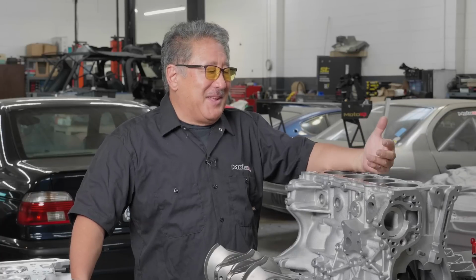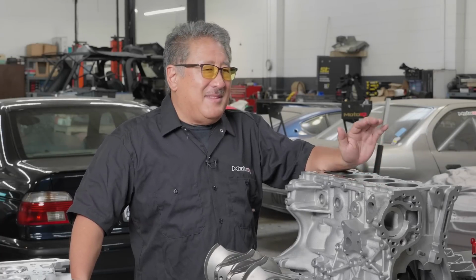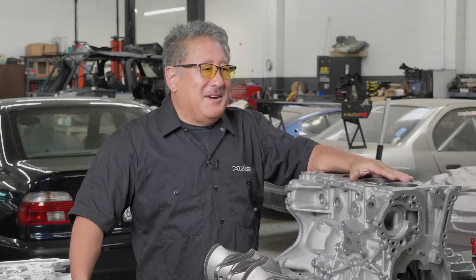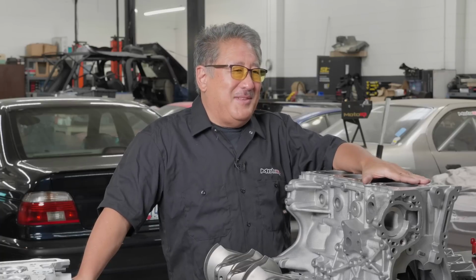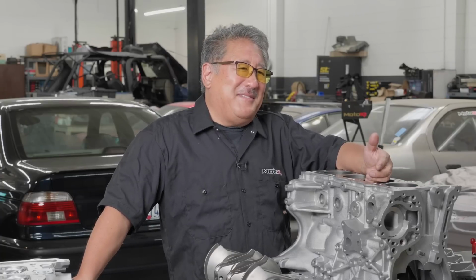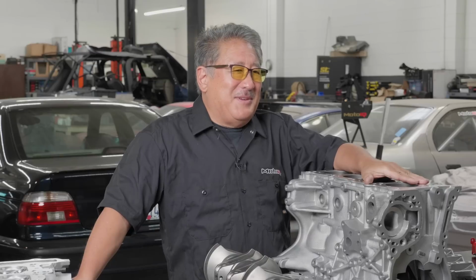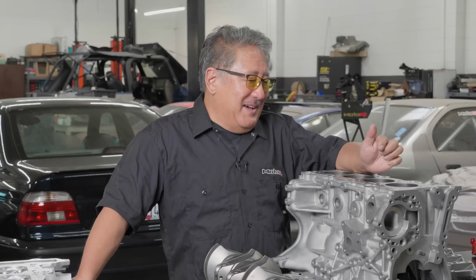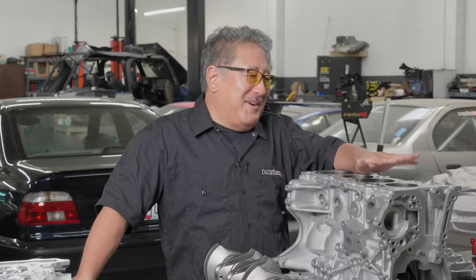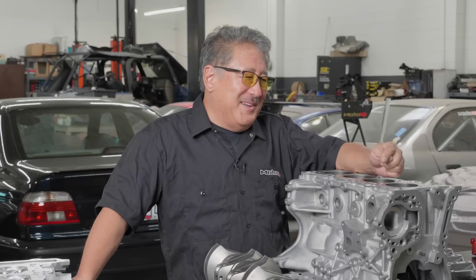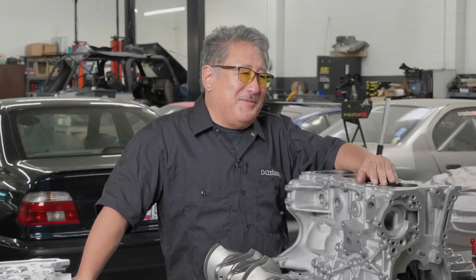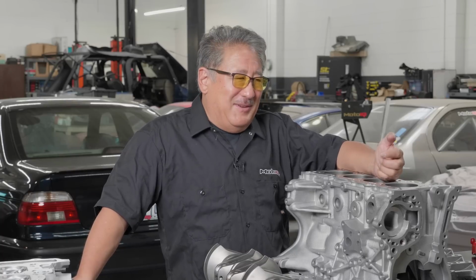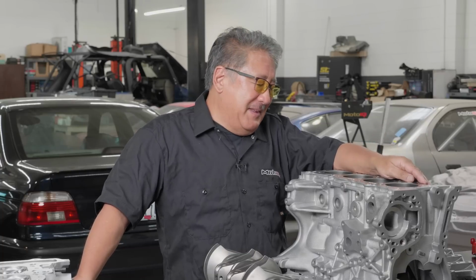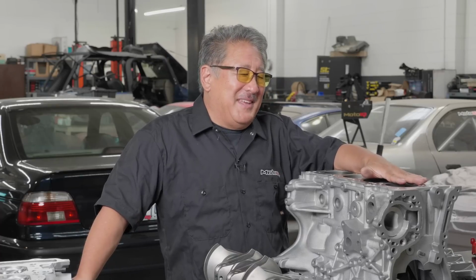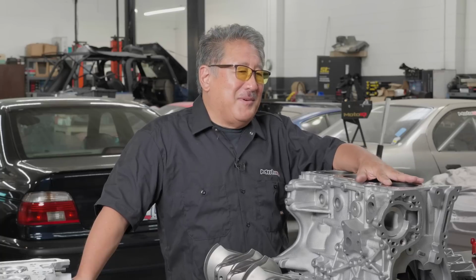In addition, after boring and honing with the correct fixturing, we subjected our bores to WPC treatment. If you watch some of our videos on our series engines, we do this a lot. WPC is kind of like microblasting. They blast the surface with a special secret ceramic media that's really small, and they mix it up with some dry film lubricant, so you get a really small surface imperfection finish with some dimpling. The dimpling is also good for lubrication retention. It's really smooth, and you have dry film lubricant blasted into the surface of the metal. It also does localized work hardening and grain refinement, so you reduce friction and your wear is greatly improved.